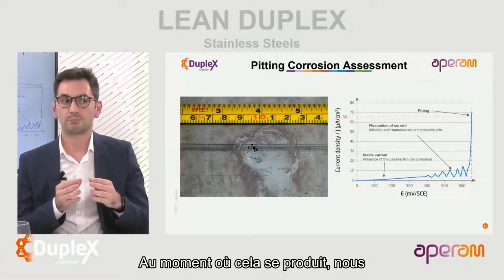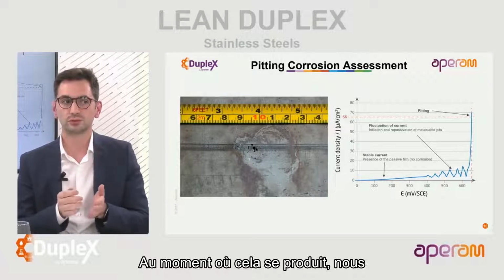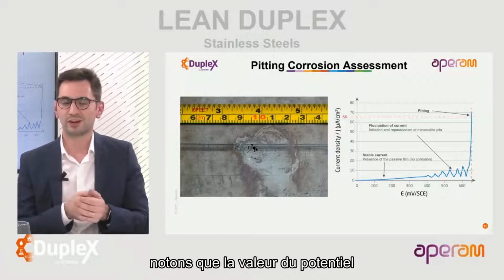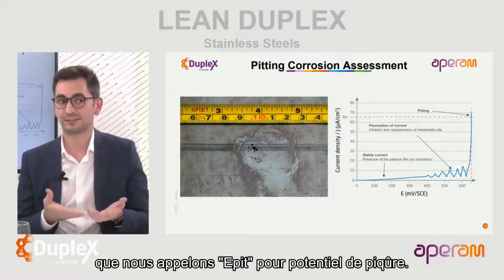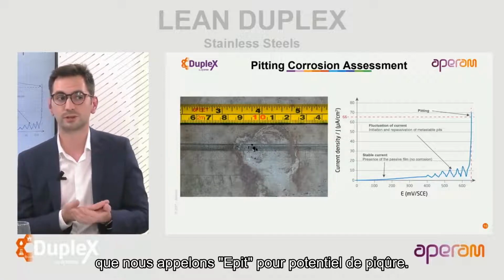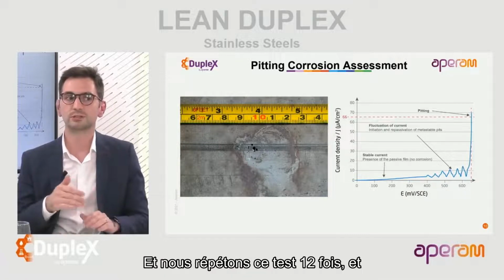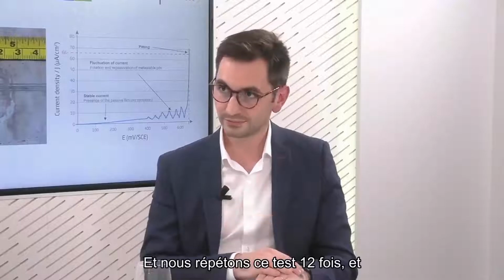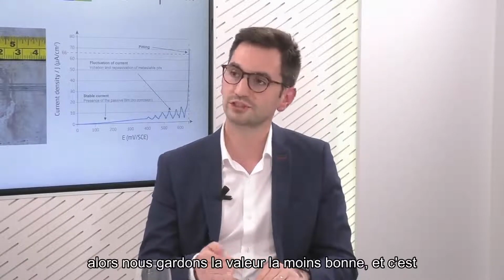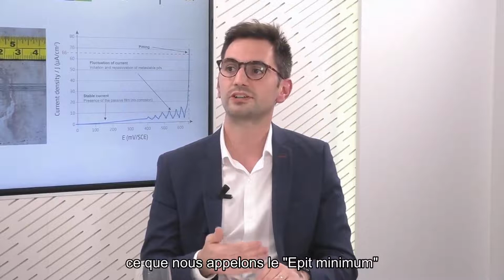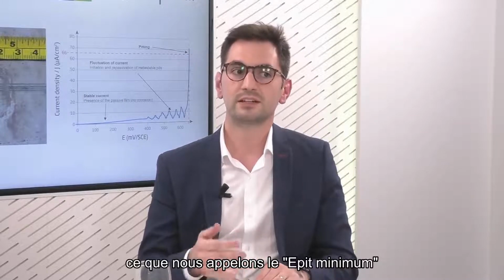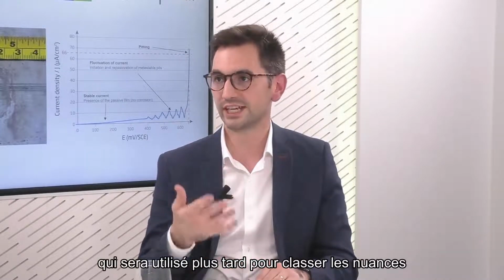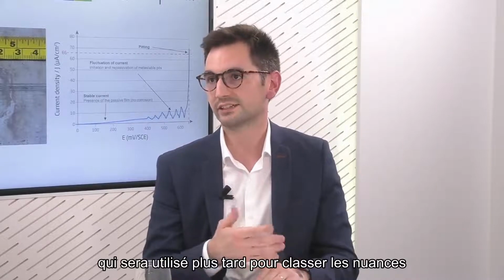So the moment when this occurs, we note that value of the potential that we call E-pit, for pitting potential, and we repeat this test 12 times. Then we keep the worst value, and that is what we call the E-pit minimum, that will be used later on to rank the stainless steel grades.